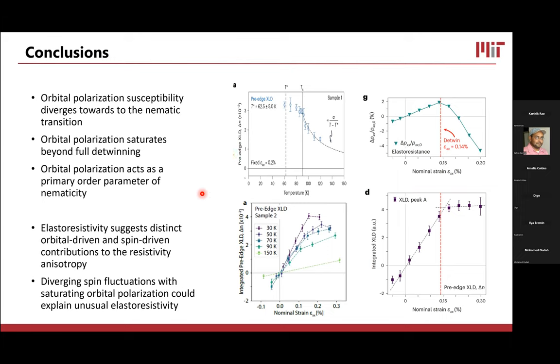Okay, so in conclusion, I showed you a collection of data using strain and X-rays in iron selenide, where we find that the orbital polarization diverges towards the nematic transition, and it saturates once we apply enough strain to fully detwin it. As we get colder, below the transition, the value also increases towards its own natural saturation value. And from these pieces of data, I would suggest that orbital polarization plays the driving role for nematicity. So we can call it the primary order parameter of nematicity for the ambient pressure iron selenide parent compound.